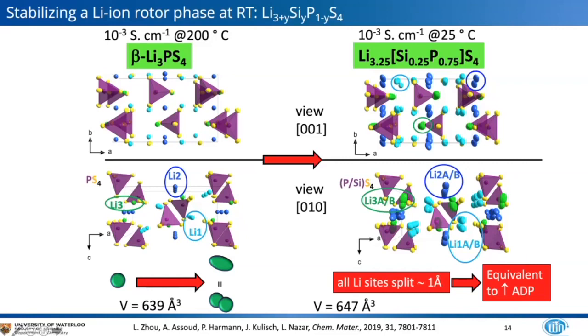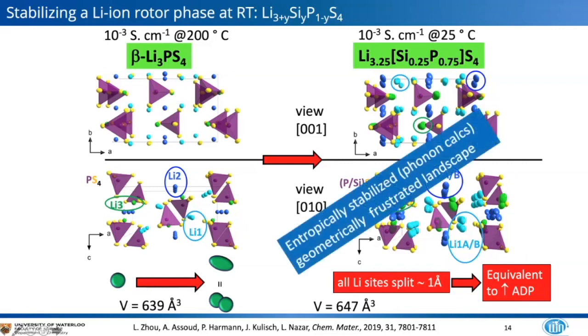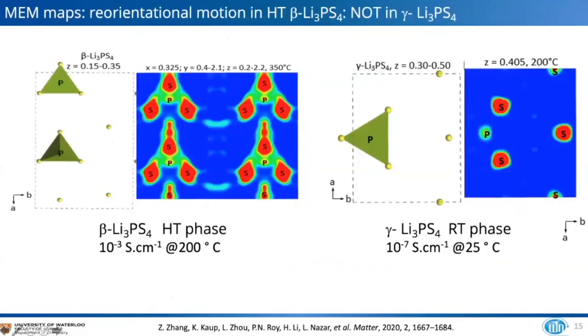And this increases the lattice volume considerably, and it stabilizes this effectively beta Li3PS4 type structure. So this is an entropically stabilized lattice with a geometrically frustrated landscape. And you can see in the gamma form of Li3PS4, which is a very, very poor conductor, 10 to the minus 7 Siemens per centimeter at room temperature,